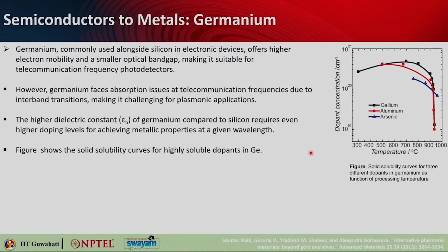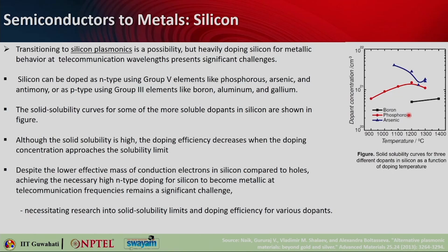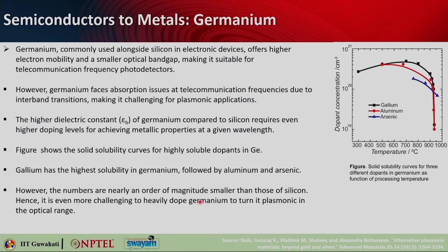Okay. So, the solid solubility curve for highly soluble dopants in germanium is shown here, and you can see that gallium has the highest solubility in germanium, followed by aluminum and arsenic. So, if you go back and compare this with silicon, there arsenic had the highest solubility and boron had the lowest one. However, the numbers are nearly an order of magnitude smaller than those of silicon. So, you can actually see the dopant concentration and compare. Hence, it is more challenging to heavily dope germanium to turn it into plasmonic. So, if they are getting saturated, you cannot dope beyond that, right. So, it means it is difficult to dope germanium to the level you can do for silicon. So, it is difficult to turn it into plasmonic in the optical range.